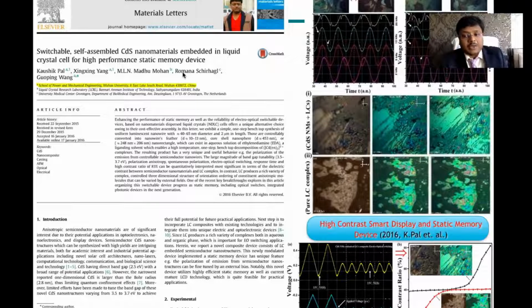high performance static memory. You can see many people say they are working on liquid crystals. These are pure liquid crystals. You can see the resolution. The resolution is very low when it is a pure liquid crystal. When we disperse the liquid crystal into our high quality nanowires, you can see our resolution easily increases. It's called contrast ratio. Through dispersing of nanomaterials, our contrast ratio is very high. It is measured by an oscilloscope. You can see the graph, contrast ratio versus time.